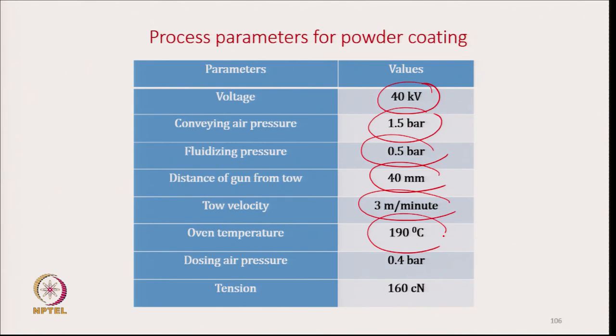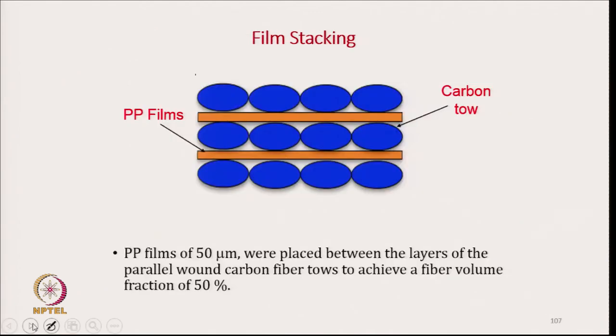Otherwise, at 200 and 220 we have seen that flexibility reduces, because ultimately we have to use this powder coated tow for weaving. Dosing air pressure 0.4 bar and tension 160 centinewton. For film stacking, this is the carbon tow, the blue color, and alternately one carbon tow layer and one film layer we have used.